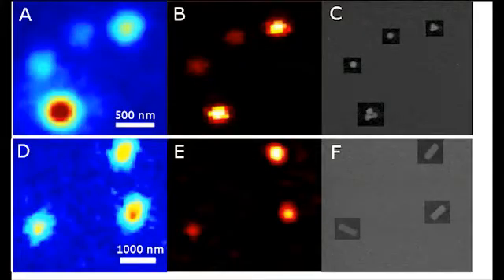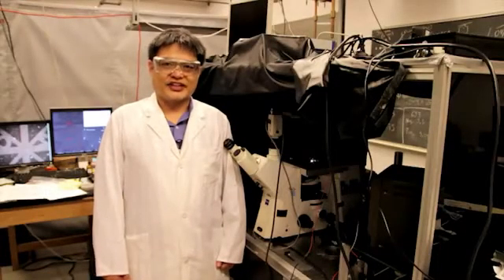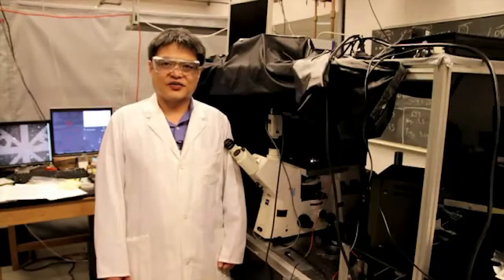Because the scattering signal scales with the volume squared and the absorption signal scales with the volume, the absorption measurement is more sensitive for small nanoparticles. With these techniques, we can characterize the radiative and non-radiative properties of nanostructures in our group.